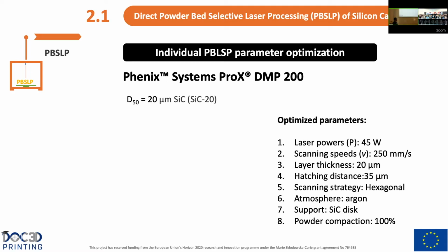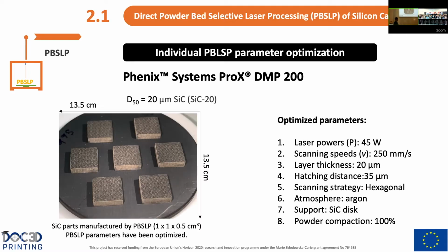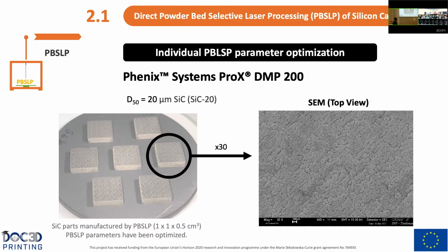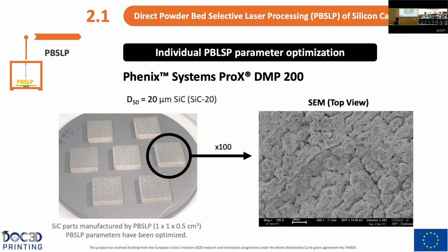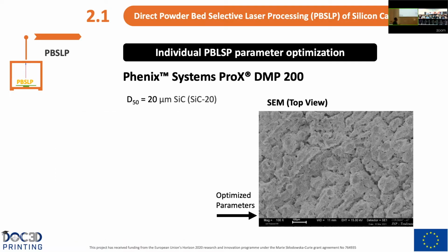And now, finally, that we have optimized all the parameters individually, we are able to manufacture, as we said, samples with a high reproducibility and the highest relative density. Regarding the microstructure of the material, here we cannot see clusters of particles or melting regions, and we cannot observe specific defect patterns either. If we zoom in, we can observe some porosity.